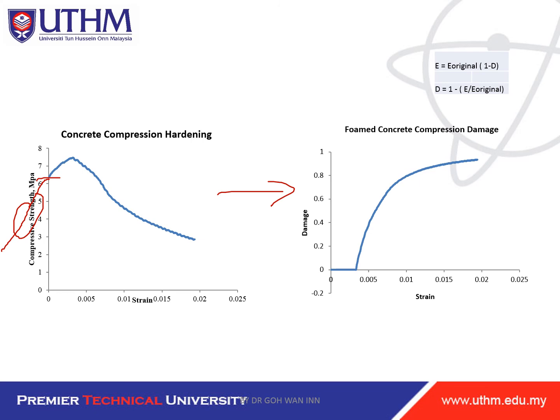You can calculate d = 1 − E/E_original and get the damage curve. However, be careful — sometimes experimental data is not perfect, and when you generate results in Excel, you may get negative damage values at certain points. This will give errors when input into Abaqus. You need to smoothen the results and edit values to remove any negative damage values. The diagram shows E_original and E for each point, calculated from the start of inelastic strain.